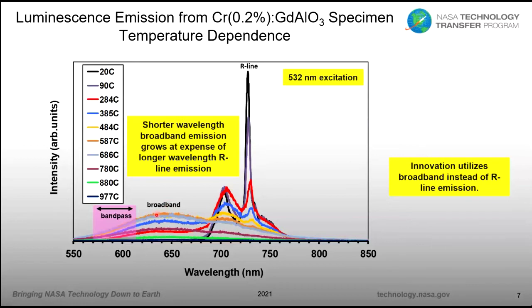Now, if your sole object was to maximize the amount of broadband emission to collect, you would collect this entire spectrum. But we decide to collect just on the short wavelength end of that. And that's because of the thermal radiation background. When that's strong, that tends to be strong in the red and in the infrared, and not too much down at the shorter wavelengths. So by picking this, we get away a lot from the interference of thermal radiation.